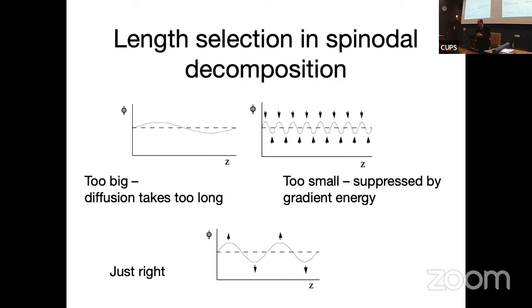You get material going from low concentration to high concentration, and any fluctuation in concentration is magnified, because any time there's a little bit of a fluctuation in concentration, that gets magnified, and you get two different phases appearing. And there's a very elegant mechanism which selects a length scale, which means that a single wavelength dominates the pattern. And this is just one of these typical balancing things.